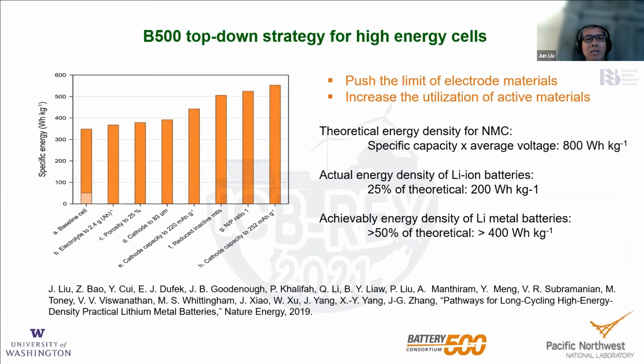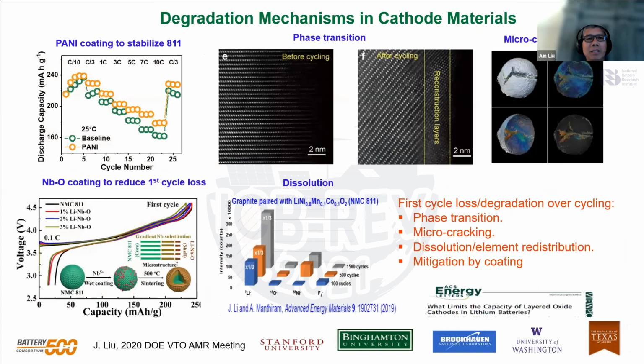I will just skip most of the things, but show you two examples. One, we take the cathode material we are studying for lithium-ion batteries, but to use it in high energy cells, we need to stress the material to the extreme. When we do this, for example with very long cycles, the particles begin to degrade. We begin to have a surface transformation. We have a big team, including Professor Shirley Meng here and Professor Stan Whittingham, and many others, who try to find ways to solve this degradation problem and stabilize the cathode material. For example, putting a coating on the surface so that we don't have this kind of degradation at the electrode level. That's one thing we do.